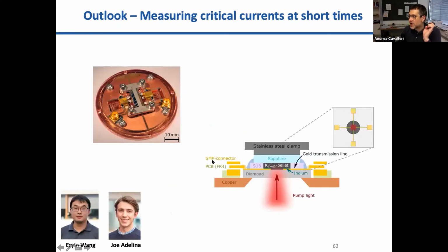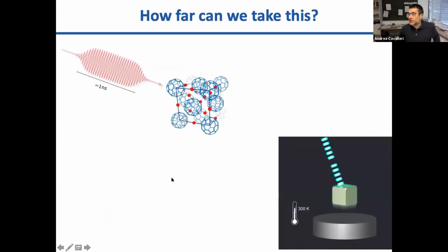And also other work that is going on are advanced measurements in which we're trying to measure critical currents at short time scales. So this is, again, work in progress. So how far can we take this? I suppose that what one should try to do, if I can make a 150 Kelvin superconductor for 10 nanoseconds, the dream would be to take a material at room temperature and use an excitation protocol to keep it superconducting in steady state. And, you know, it doesn't hurt to dream. And this is really the ultimate goal that this type of research in this specific material is leading us to.